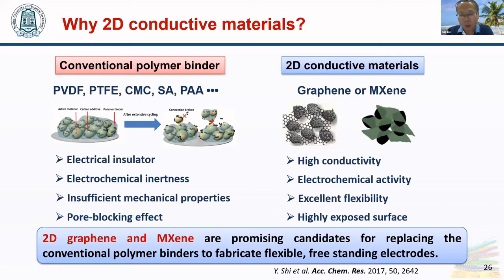Using 2D conducting materials like graphene and MXene can solve this problem. Graphene and MXene have very high conductivity and electrochemical activity, excellent flexibility, and highly exposed surface. So they can act as conductive actives and also a flexible backbone. So it is expected to obtain better performance and good flexibility. So 2D graphene and MXene are promising candidates for replacing the conventional polymer binders to fabricate flexible freestanding electrodes with superior performance.